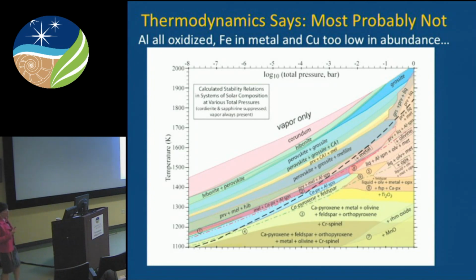why not. So here, if we're condensing in an oxygen-rich atmosphere, the aluminum is going to come out either as corundum or hibonite as you keep cooling. It's going to come in oxidized form. The iron will not be mixed with the aluminum. It's going to be in metallic iron. And the copper is just too low in abundance to have formed this major phase of aluminum copper iron. So the thermodynamics says, wow, this is a really unlikely scenario: to find major aluminum oxide-rich phases coexisting with metallic aluminum that's also alloyed with a cosmochemically much less abundant material, copper, which has very different redox preferences or conditions. So thermodynamics is probably not it.